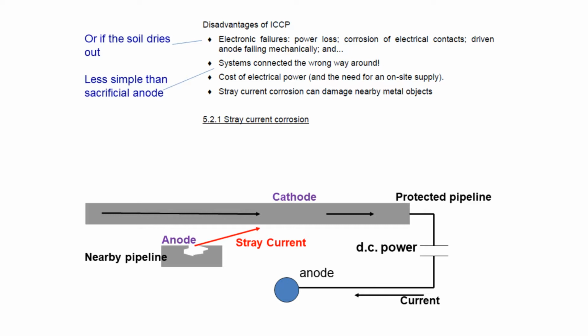One of the more frightening possibilities that can go wrong with ICCP is that, unlike with a sacrificial anode, which you just bolt to the side of the system you want to protect, it is possible to completely mess up with an ICCP system. You could connect the electrodes the wrong way round. People have done this in the past, and you might find then that your thing to be protected, which you meant to make into a cathode, has been accidentally connected as a driven anode, and it's actually being destroyed by an improperly installed ICCP system. So it needs qualified and fairly skilled installation.